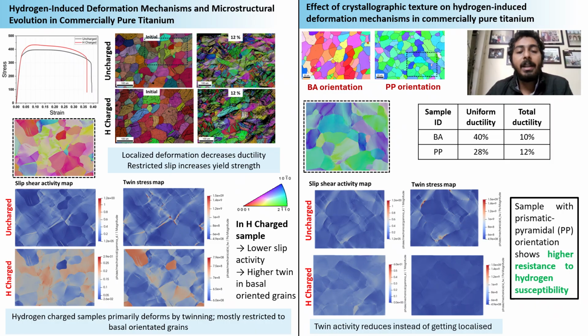So for this we did in situ tensile testing, in which we do the tensile testing inside the scanning electron microscope, from which we found that there is a reduction in ductility, and this was due to the localized deformation that is occurring in the basal oriented grain, that is the red color grain, which is responsible for the reduction in ductility. Hence, we planned our next chapter, that is the effect of crystallographic texture on this deformation micromechanism.